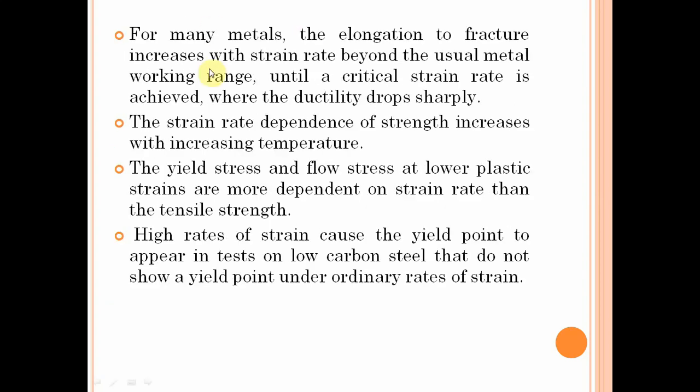Next point: for many metals, the elongation to fracture increases with strain rate beyond the usual metal working range, until a critical strain rate is achieved where the ductility drops sharply. The strength dependence on strain rate increases with increasing temperature. The yield stress and flow stress at lower plastic strains are more dependent on strain rate than the tensile strength.